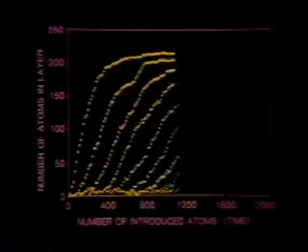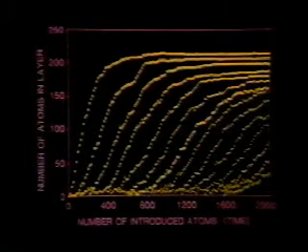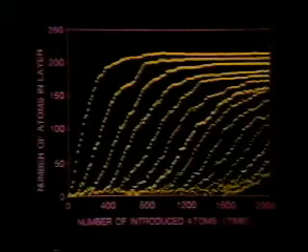It knows. At very low temperatures, Lennard-Jones particles, metals, grow in incomplete layers with a regular hexagonal arrangement in each layer. At any instant of time, a graph of particle density versus time shows a regular layered arrangement with incomplete layers. Note that sequential layers are less and less complete. The in-plane arrangement is crystalline with well-formed hexagonal patches, defects, and dislocations. The defects increase in size at higher and higher levels, the reason for the incomplete layers. This is in qualitative agreement with experiments.